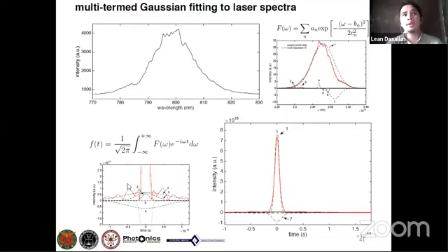This is important because in many experimental works, people will try to explain it by assuming that there's a single dominating pulse in their calculation. But in reality, there is some energy before the main pulse and after the main pulse. And this energy will drastically change the energy distribution on the ablation part.